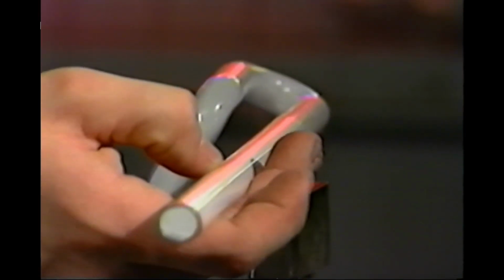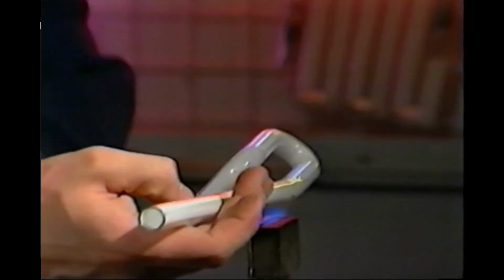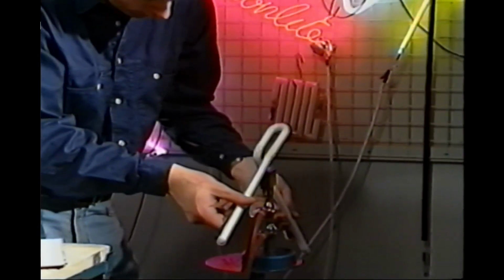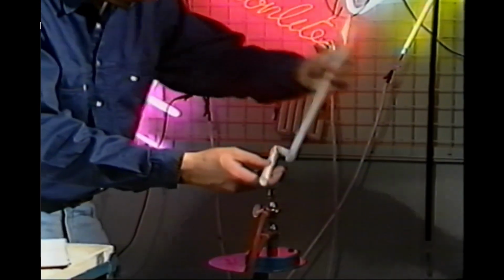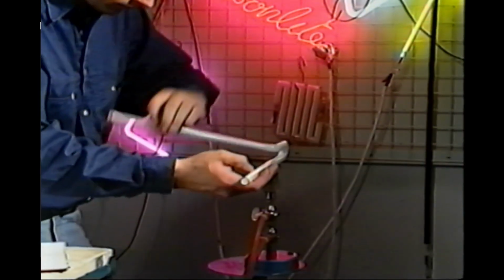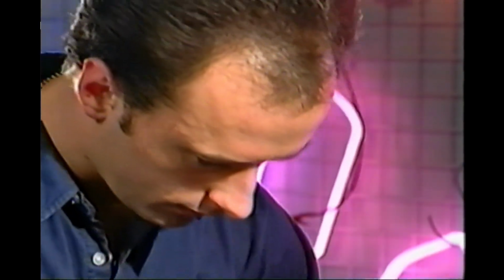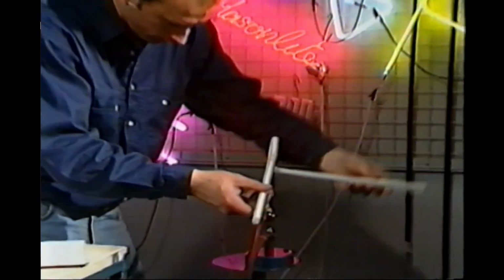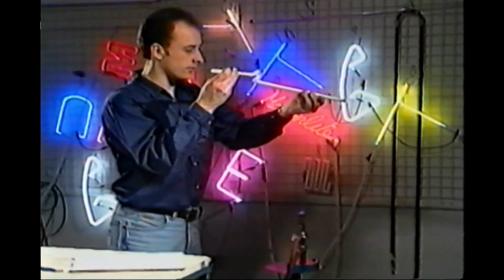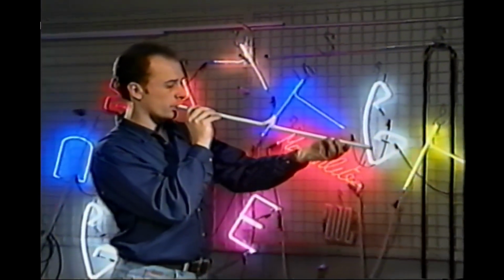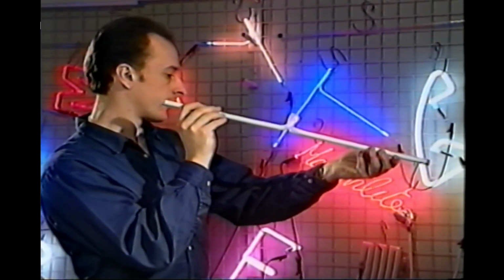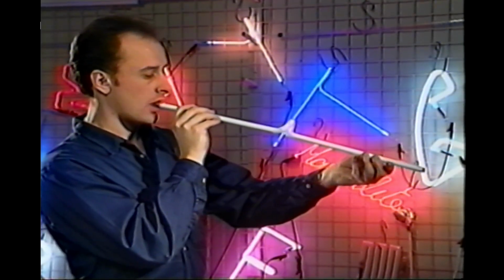Thirdly, the glass must not be allowed to stretch or thin out during melting. This will result in fragile bends, as well as thinning of the phosphor coating around the bent area. Finally, the actual forming of the bends. After heating, simply folding the glass will create poorly formed bends. The glass must be bent by correct movement of the hands to enable the required shaping to take place to achieve good quality bends.